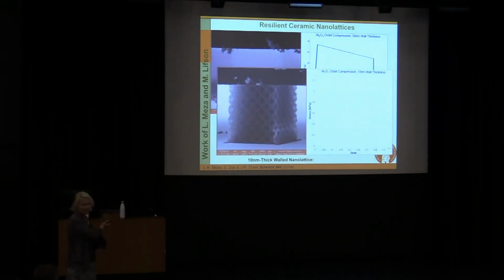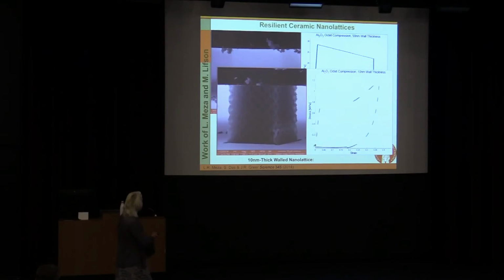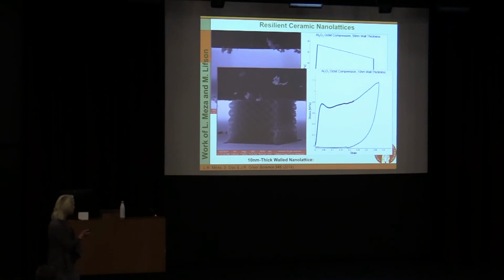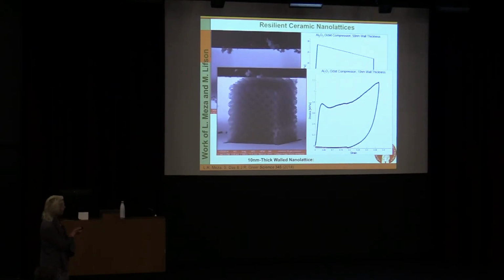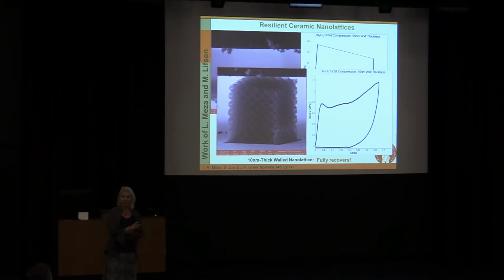So we repeat this experiment on something that should crush and die even more readily. So this is exactly the same architecture, the same process, everything is exactly the same. But now we reduce the wall thickness by a factor of 5. So it went from 50 down to 10 nanometers. And now watch what happens. So we're compressing it, we're ready for it to crush and die even more readily. And you see it's compressing it almost to halfway point, so about 50%. And now as we're approaching the point where, wait, it should be breaking, but instead it's recovering. So my former student Lucas made a ceramic sponge. This particular ceramic thinks it's a sponge.